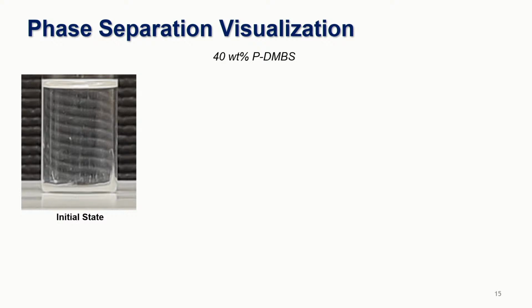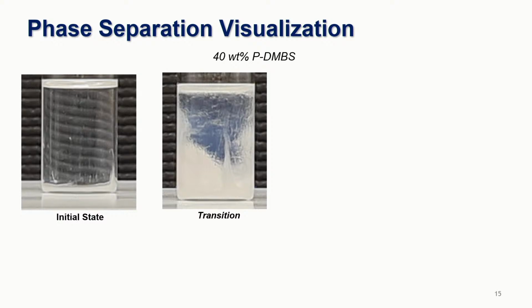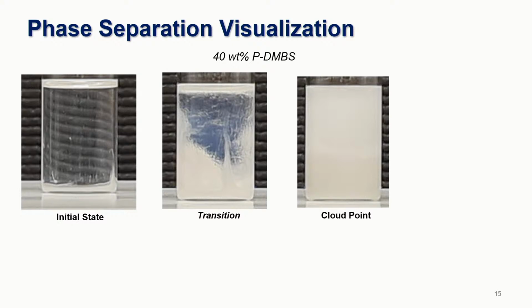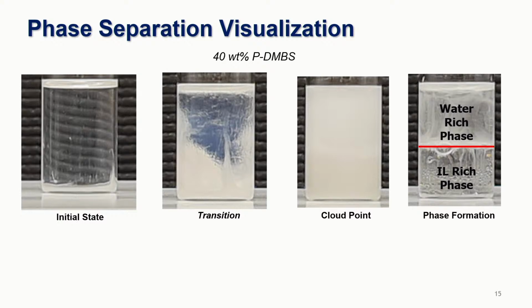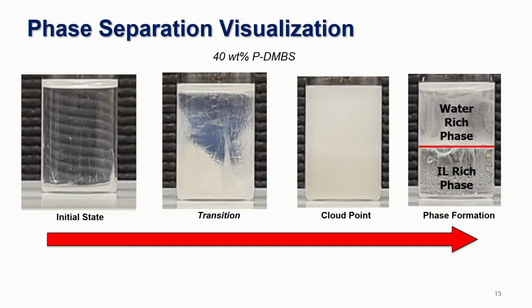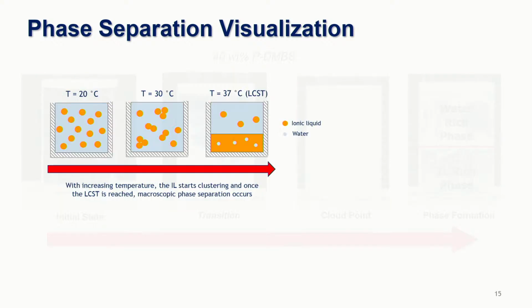So this is what that thermally driven phase separation looks like. So this is the ionic liquid and water mixed at room temperature. And you can see it's a single phase mixture. As we start heating it, it forms almost like a milky solution. And so that's what we call the cloud point temperature. And then finally, after the entire solution is heated up to that critical temperature, we get the two layers to separate. And there is a discernible phase boundary, and the water-rich phase floats on top of the ionic liquid-rich phase. And so temperature enables us to go from this single phase mixture to the two phases.